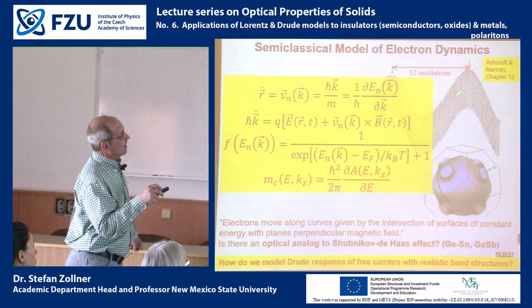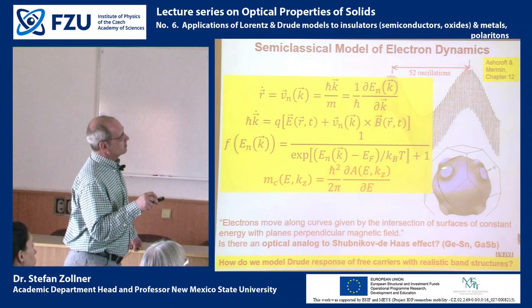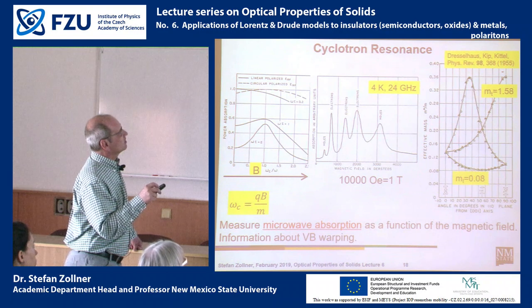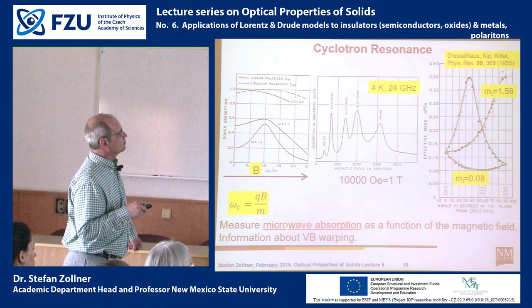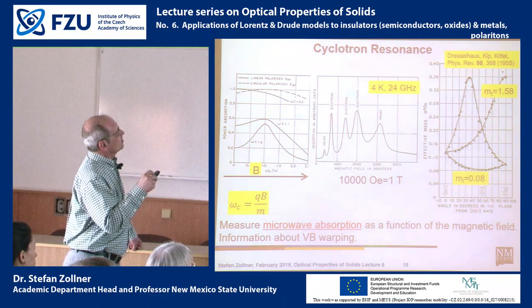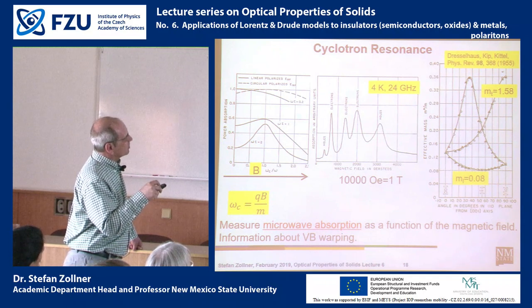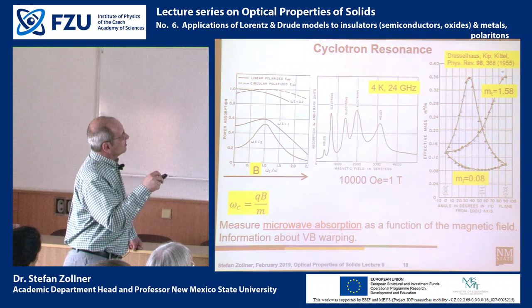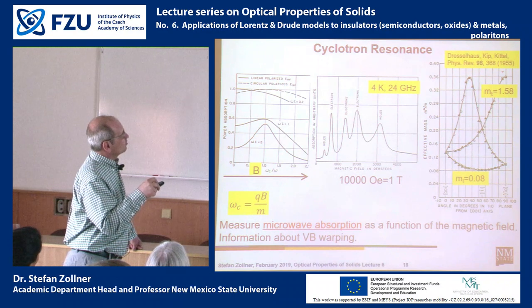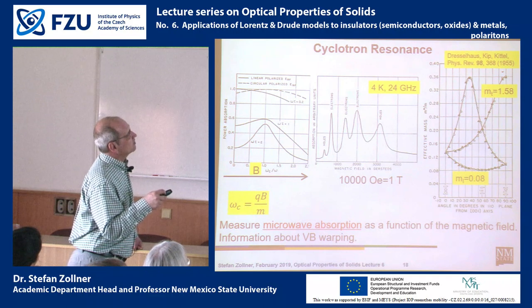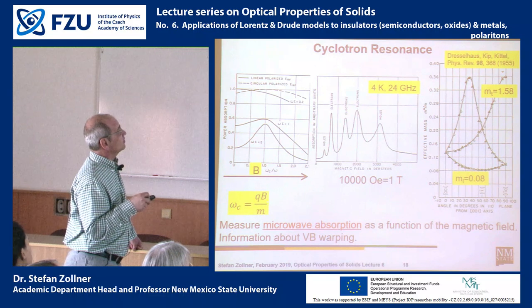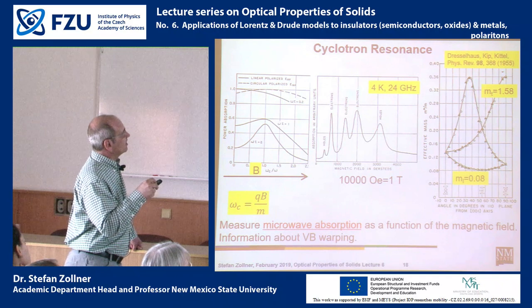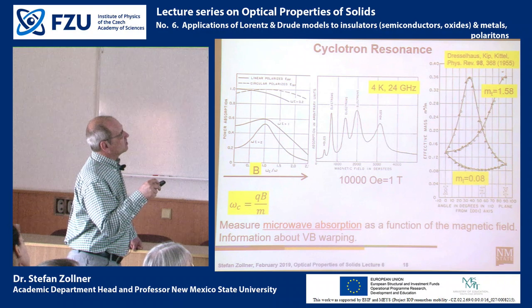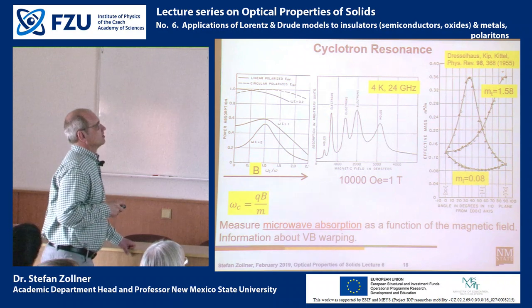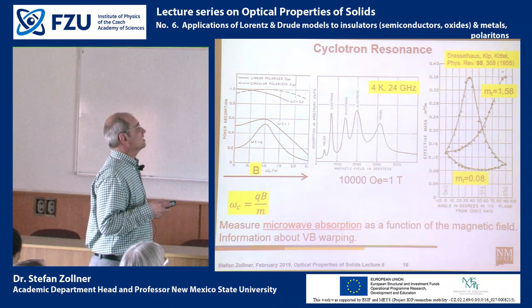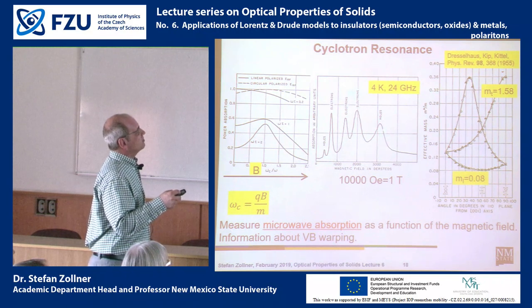The way that people have mapped out these oscillations has been using cyclotron resonance. Cyclotron resonance means that you measure the microwave absorption as a function of the magnetic field. If you measure the absorbed power versus magnetic field, then you get these peaks, whenever the frequency of the microwave that you apply, in this case 24 gigahertz, equals the cyclotron frequency. Then you get an absorption peak. Because you have different types of carriers in your material, electrons and holes with different types of masses, you get multiple peaks.